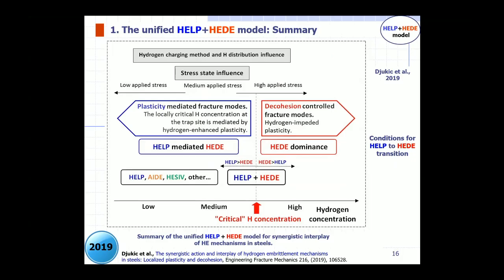Here is the overview of the HELP plus HEDE model published in 2019. As you can see, depending on critical hydrogen concentration, which is on the x-axis, at lower concentration we have some plasticity-mediated mechanism activity, including HELP, AIDE, HESIV, and probable HELP-mediated HEDE. So the local critical concentration is governed by the activity of plasticity-mediated mechanisms, but when we approach critical hydrogen concentration, we have a transition to so-called decohesion dominance, which means that decohesion becomes dominant, which doesn't mean that we don't have ductility. We still have some sign of HELP or some other mechanism, but from microstructure point of view and from engineering point of view, the influence of ductility provoked by hydrogen becomes minor.